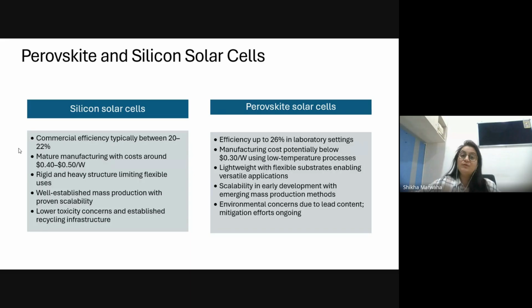And even if we are able to retain 90% of this efficiency for a period of 15-20 years, that's actually a good thing. In case of perovskite, we are not having anything in terms of commercial level. We are still at the laboratory settings, and we can obtain an efficiency of 26%, near about. Silicon is a very matured manufacturing technology, because, as I've already said, 95% of the market of photovoltaics is dominated by silicon.